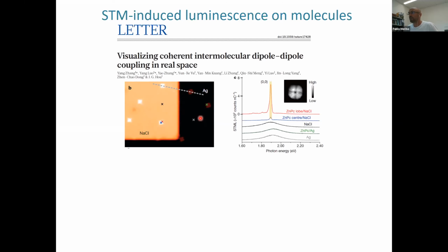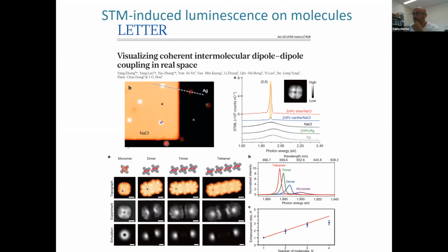And in this paper, here we have another photon map, and we see the emission, which is a sharp line at a particular energy. And what they found here is that these molecules are extremely sensitive to their environment. And they demonstrated this by putting molecules together. Here we have an example where they manipulated single molecules to get chains of up to 4 monomers. And they saw in the photon maps, where the lighter is the higher intensity, and very importantly, that the energy of the emission changed depending on the number of molecules. So 4 molecules together do not emit like 4 molecules isolated. It changes the emission, and this is because you are coupling the molecular dipoles, and you are getting a new quantum emitter, a supramolecular quantum emitter.